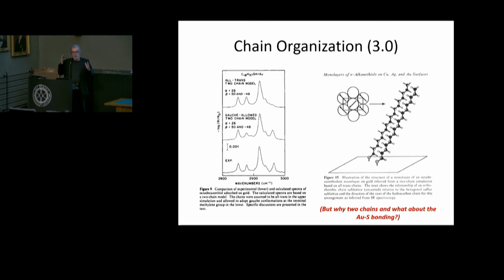And the reason why it's gold 111, when you evaporate the film, maybe you have everything, but it turns out that a thermal evaporation produces a really strong fiber texture. So most of the grains that you have are presenting with a 111 orientation, very strongly so. And you can actually manipulate that as part of the procedures that you use for preparing the underlying substrates. And the chains organize on that, but it also turns out that the chains organize based on their pairwise interactions. The lateral interactions drive another level of organization in materials. And it was also clear from the data shown here that pairwise interactions involve an underlying orthorhombic sublattice that involves chains oriented at 90 degrees relative to one another.